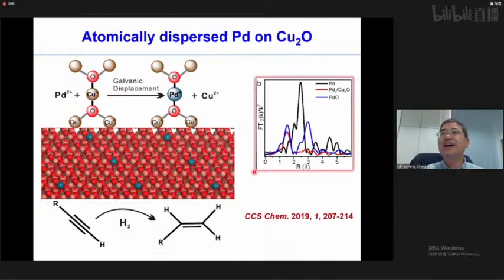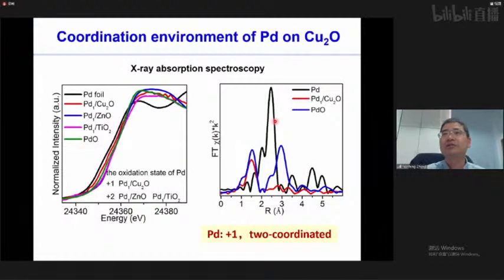On this metallic copper, as you can see here, the CO vibration frequency, the wave number, is much lower than on copper(I) oxide, just because there is a difference in their oxidation state. You might know that in copper(I) oxide, all these coppers are linearly two-coordinated. So if we put palladium in to replace this copper, it will keep this +1 and two-coordinated structure, which is confirmed by our X-ray absorption spectroscopy studies, both their oxidation states and also the coordination structures.